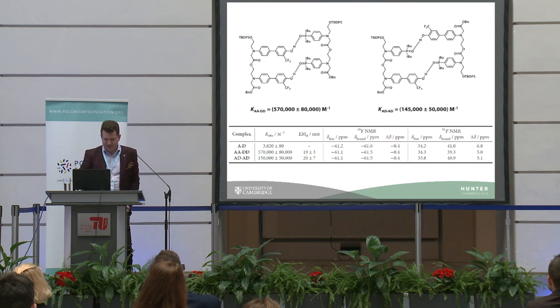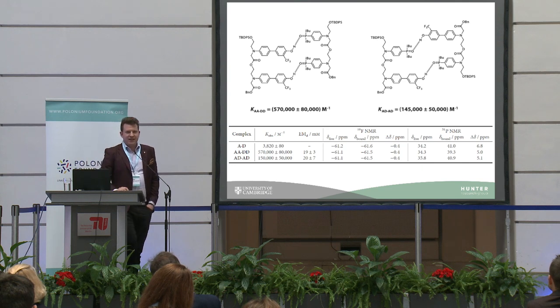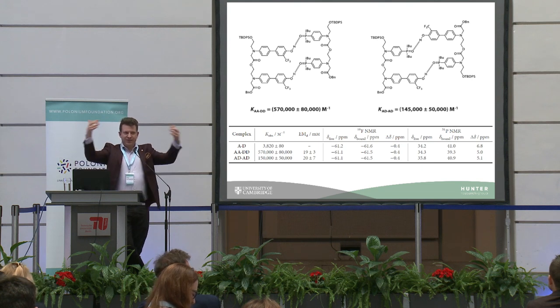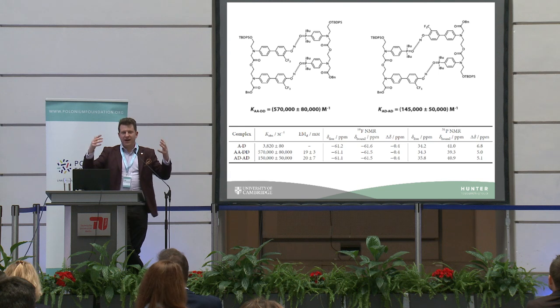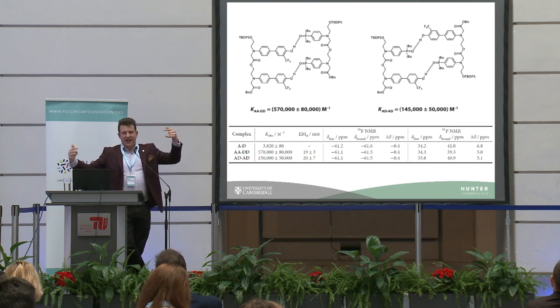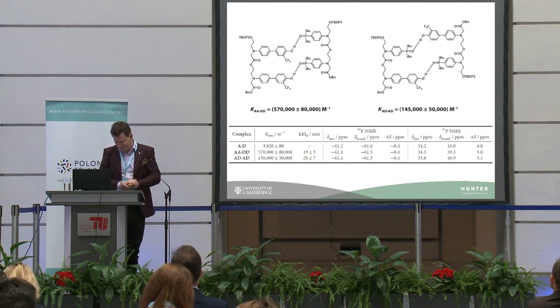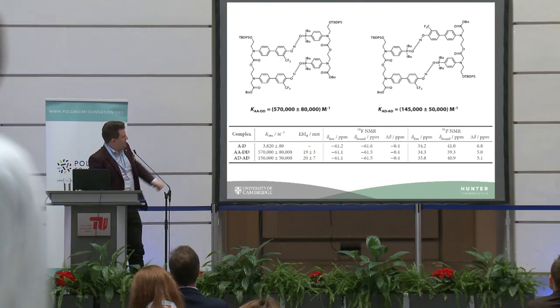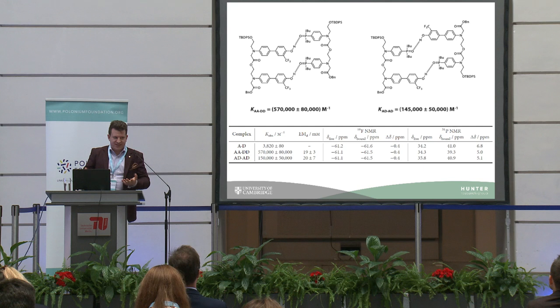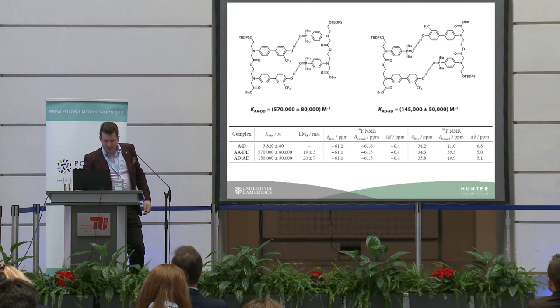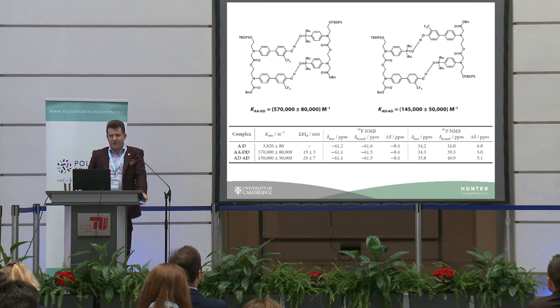The other data shown is to demonstrate that both the donor sites and acceptor sites show a very strong change in the magnetic field they experience upon the molecules coming together — meaning both are involved in bonding. It is not just one chain doing something while the other is elsewhere; they do come together and form a closed duplex. Similarly, the AD chain and DA chain self-associate, with a binding constant much greater than for isolated hydrogen bonds, so it must be cooperative. No folding is observed.